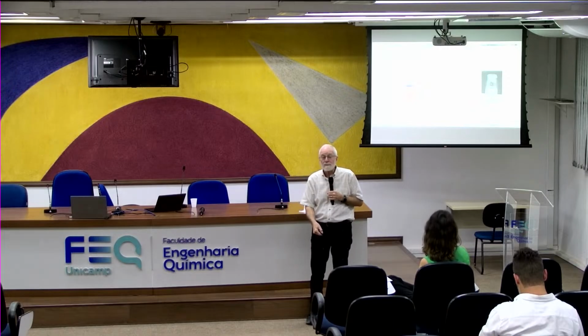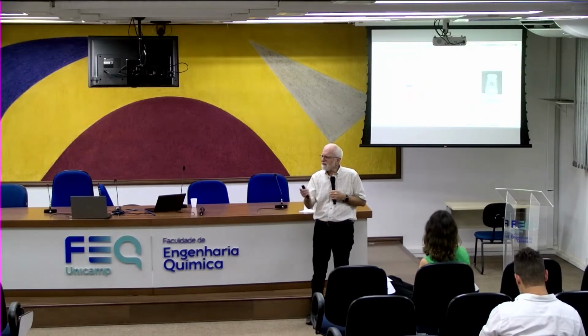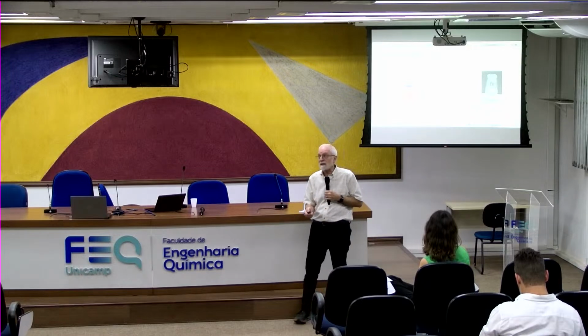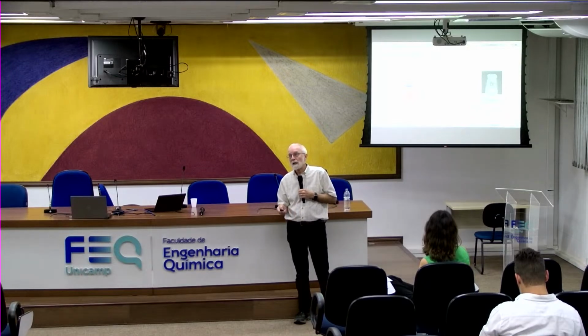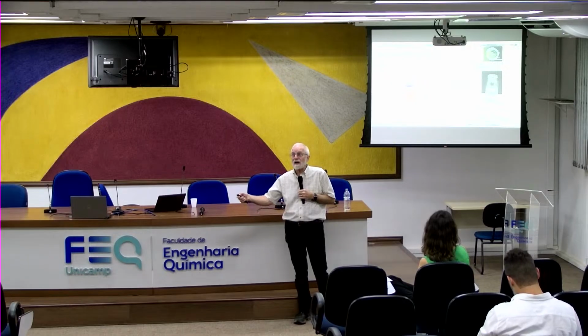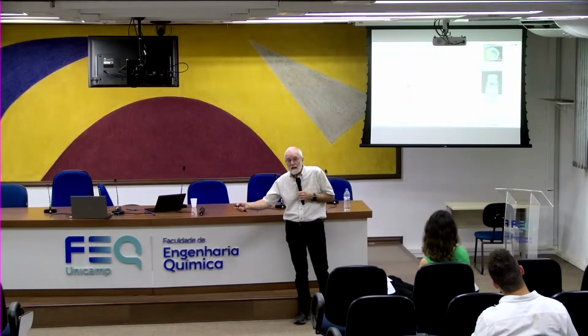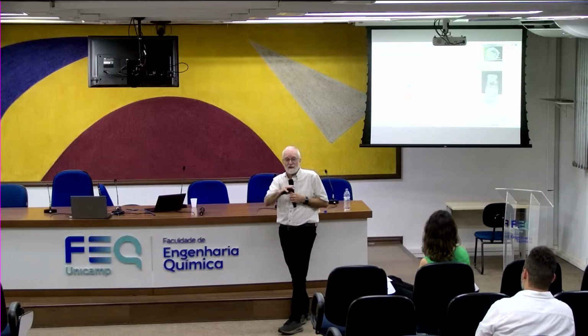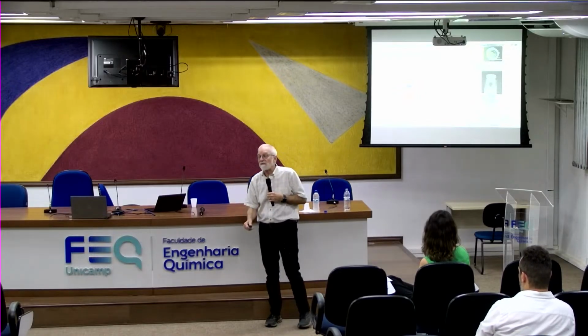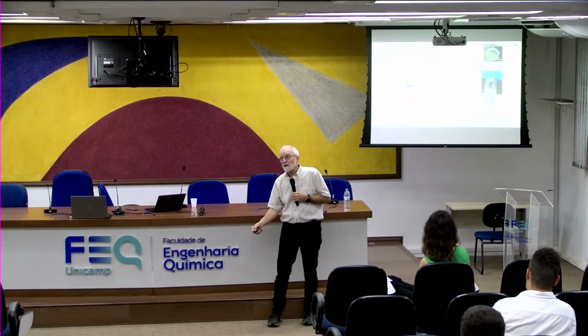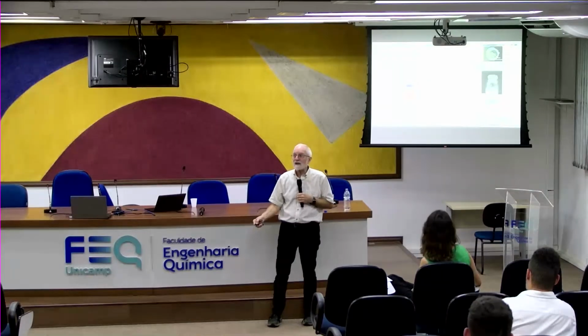It's over there. And that's a very mild process. The body in nature handles this extremely easily. So we said, could we play that game with silicones? So we buy silicones. We actually buy this material. It has sulfur already on it. You add an oxidation agent that leads to now the disulfides. Then you can use a chemistry that we developed to cleave those sulfur-sulfur bonds to give you back a silicone oil, but actually you have to add water.